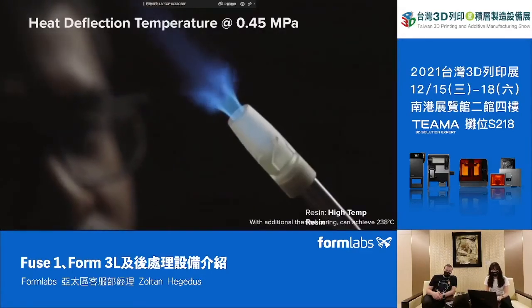I already kind of mentioned why we need the Cure L, but just to say a few more words and give you a couple more examples. Let's look at our high temp resin. High temp resin, before curing, only has a heat deflection of about 49 degrees Celsius. But after post-curing, it can actually achieve 120 degrees. And with some additional thermal curing, you can go up to 238 degrees Celsius.